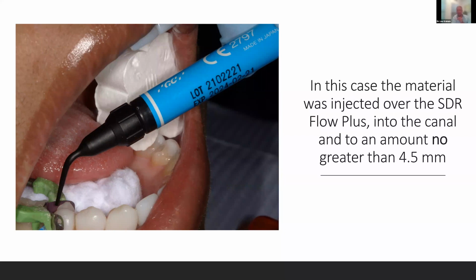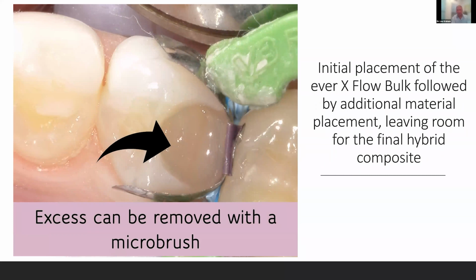So in this case, I injected this over the SDR Flow Plus into the canal, and I definitely did not put more than 4.5 millimeters of material as far as height goes. I'd say it's probably 2 to 3 given this preparation on a bicuspid. So I'll inject 2 to 3 millimeters because I've got to leave room for my final capping layer. And there you can see it. I'm leaving about 2 millimeters for my final capping layer.